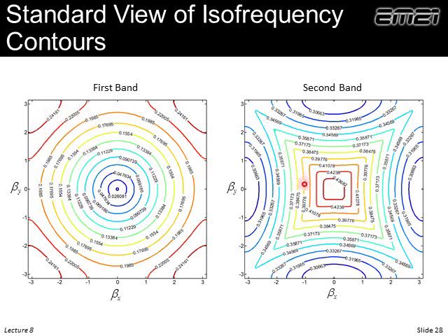Second order band, this is pretty cool. We already know that these flat regions are very interesting because that's where self-collimation happens. So there is a lot of information here. And even sometimes these curves here are very interesting because we can cause negative refraction to happen just due to the dispersion in the lattice. We don't have to have a negative refractive index for that. In fact, we'll explain this in a couple of slides.